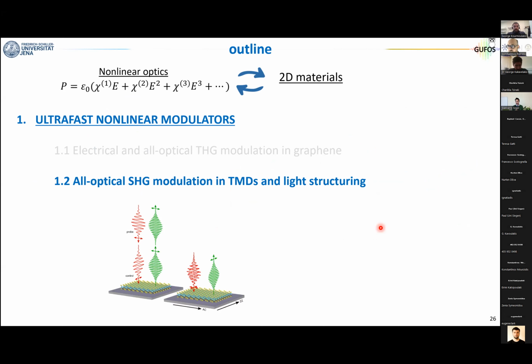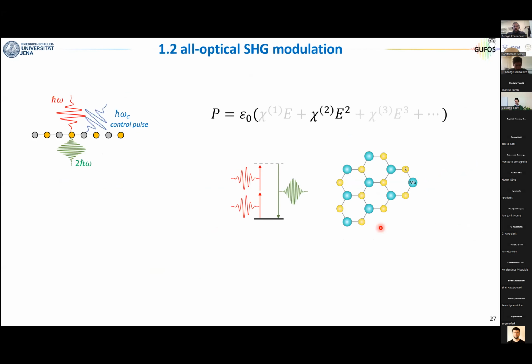So time is running, so I will move to second harmonic modulation in TMDs. Now, the idea is very similar. We again want to have a modulator, so a device where we switch on and off the nonlinearities. This time, we will be looking at the second harmonic because, again, as I said, we have a hexagon, but the two atoms in the hexagon now are different. So the space inversion symmetry is broken. In this case, we can have a Chi2. We can do second harmonic generation. So we enter with 2 photons, generate 1 photon at 2 omega.